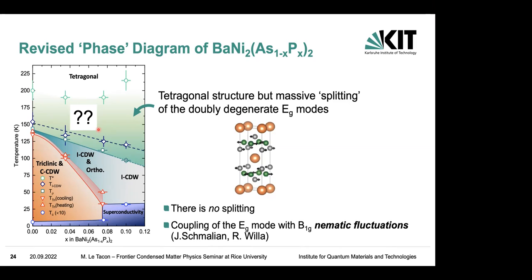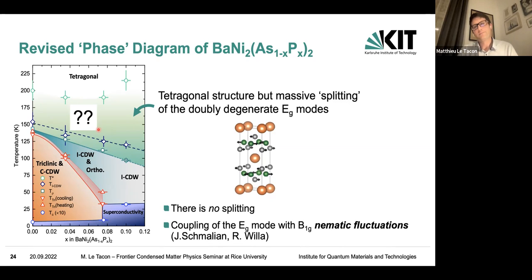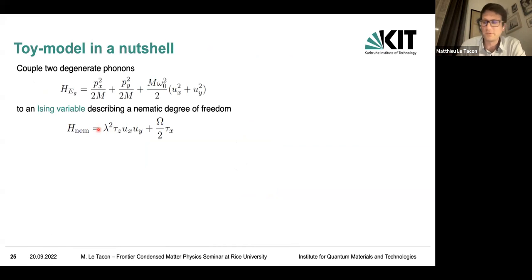And basically what he came up with is the idea that indeed you could conceive a situation where your EG mode, your doubly degenerate EG mode, can couple to fluctuation of a certain symmetry. And it turns out that the B1G symmetry is the right symmetry to couple to this EG mode. And that might give rise to an apparent splitting without lifting the degeneracy. So that was his intuition.